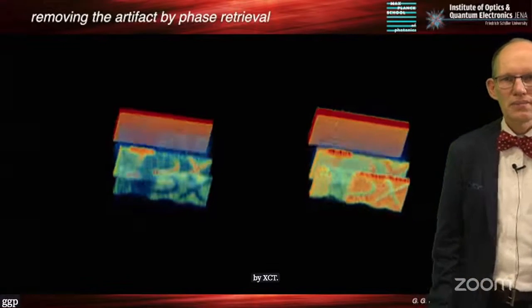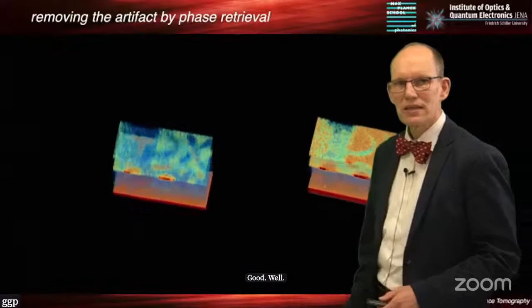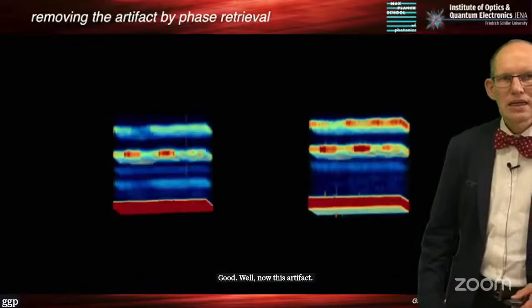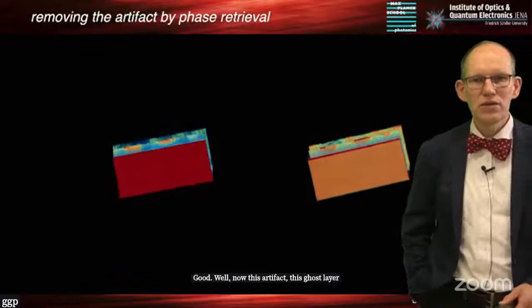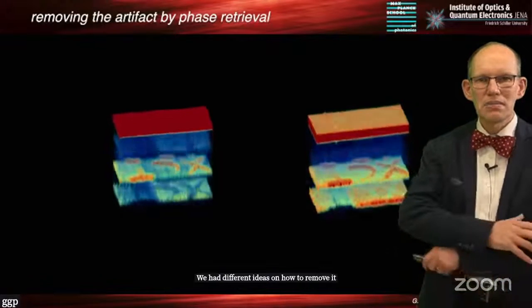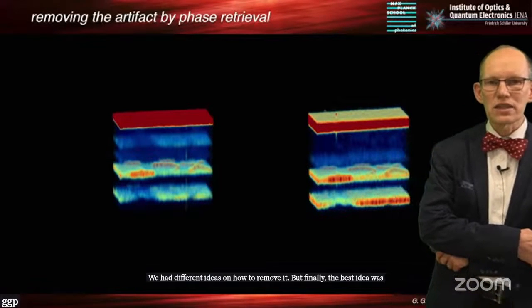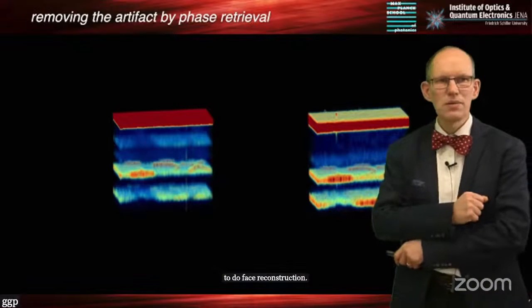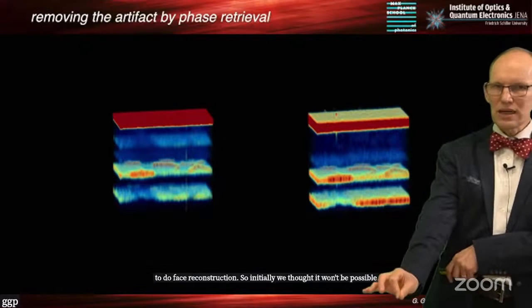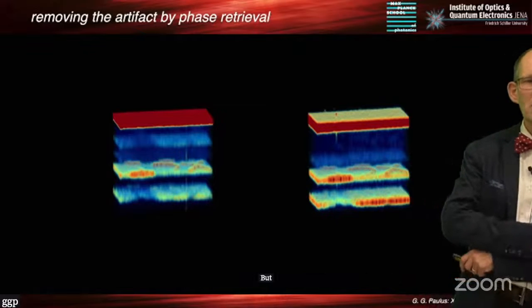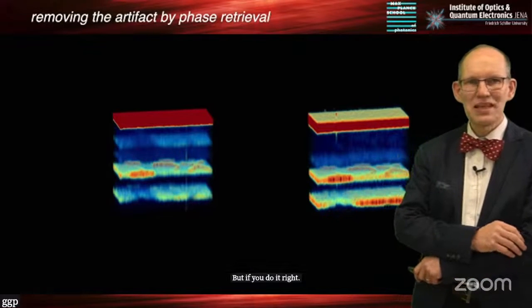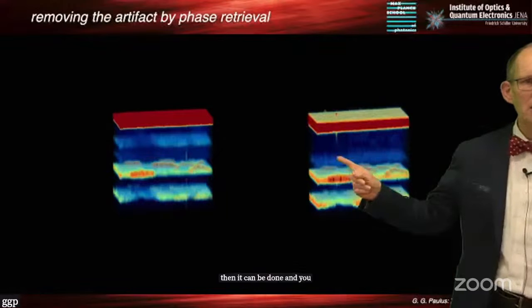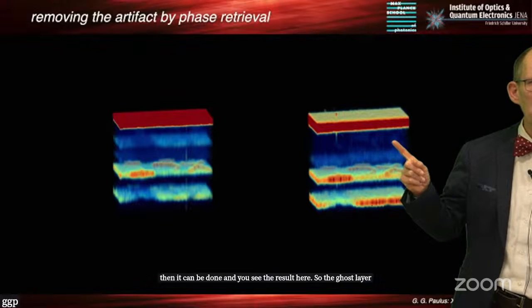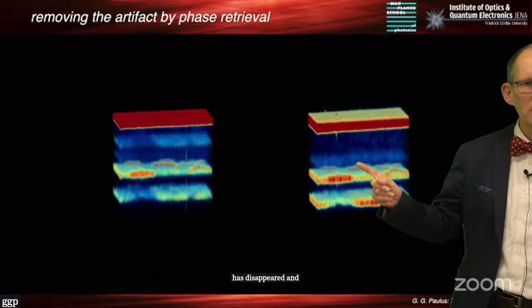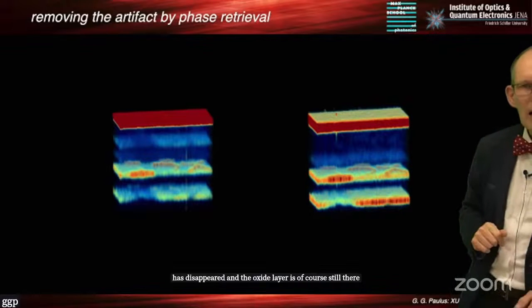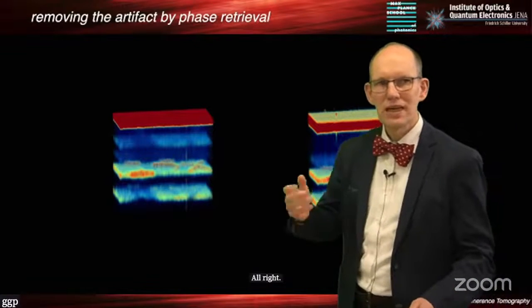Good. Now this artifact, this ghost layer, we had different ideas on how to remove it, but finally the best idea was to do phase reconstruction. Initially we thought it wouldn't be possible because it's a one-dimensional problem, but if you do it right, then it can be done, and you see the result here. The ghost layer has disappeared, and the oxide layer is, of course, still there. Very nice.